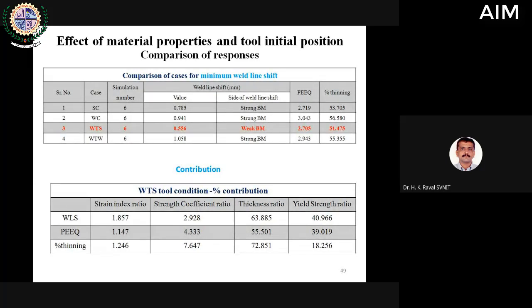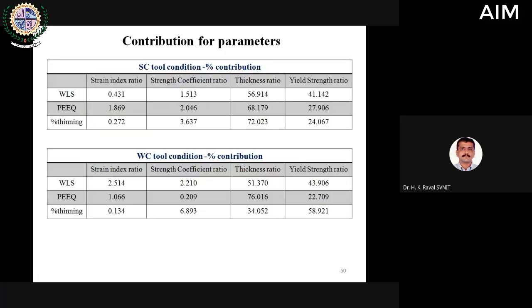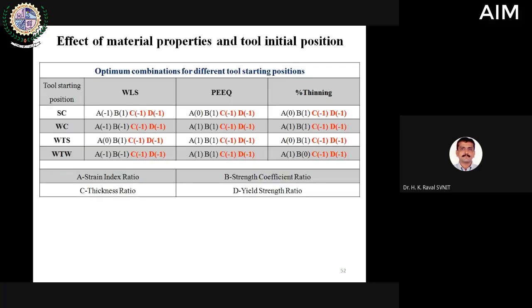And the contribution of each of these combinations is shown here. We are not going into much detail of that, but one can make out from here that thickness ratio and yield strength are more contributing parameters compared to strain index ratio and strength coefficient ratios. So these two are the more governing parameters to get the minimum weld line shift, minimum plastic strain, and minimum thinning. For all these combinations, the same is the observation. You can see here, the same is the observation. And the optimum combination is obtained. You can see it is very easy to make out. Only C and D, which are the thickness ratio and yield strength ratio, are the optimum combinations.